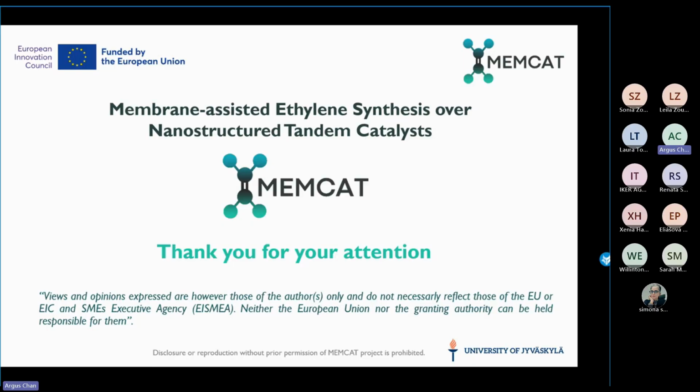All right. Then we have a question on the chat also. If you have considered the formation of copper and zinc alloys as an active site. Yes, this is what extensively has been considered in the literature, but what Annette tells us is that no, it's not an alloy. Originally, during the induction period, it's an alloy, but when you introduce the reactants, this alloy oxidizes so that you have copper and zinc oxide. So that was why we neglected it from the present study.